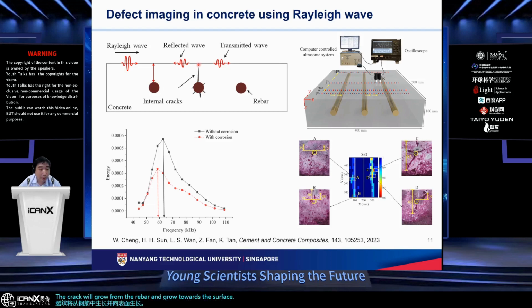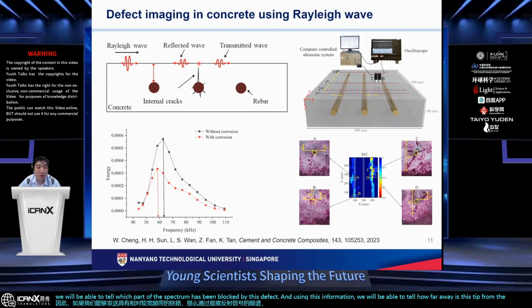So in this work, we are hoping to use ultrasonic waves to tell how severe these cracks are with respect to the surface, how far away the tips are from the surface. The idea we are exploring is to use the ultrasonic Rayleigh wave, whose energy we know is focused within around one wavelength of the surface. So if we send a Rayleigh wave with relatively broad bandwidth, then by looking at the spectrum of the reflected signal, we will be able to tell which part of the spectrum has been blocked by the defect. Using this information, we can tell how far away the tip is from the surface, and then somehow correlate it with the corrosion levels.